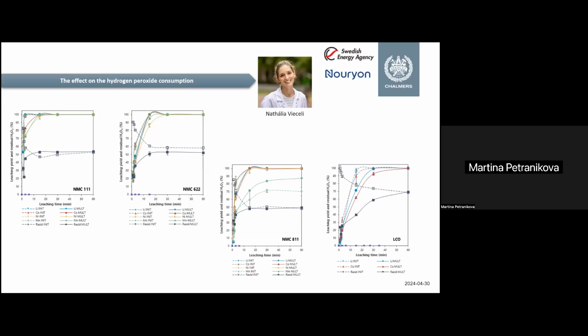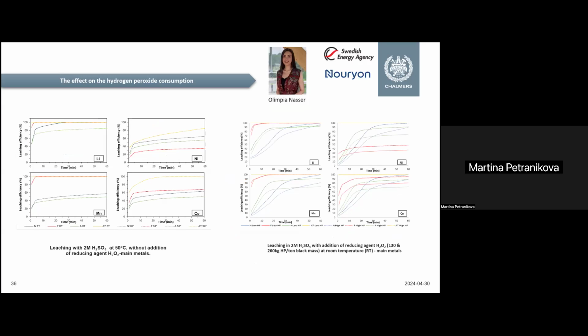The only difference was for NMC 811, where the effect on the manganese was slightly better if we multiplied the dosing. We also did research on the effect of thermal treatment on the consumption of hydrogen peroxide. We received industrial samples from different companies doing recycling in different ways, with different thermal pretreatment. The yellow line represents pyrolysis, which usually shows to be the best option as a thermal pretreatment. Red line is incineration. Green line is without any thermal pretreatment, and blue one is a mild thermal pretreatment.